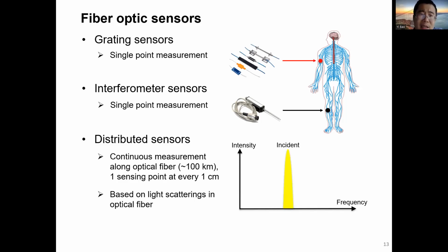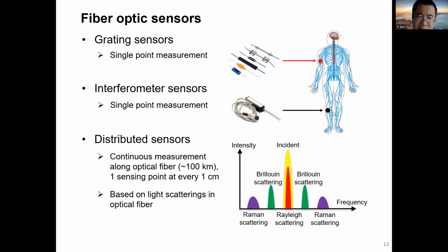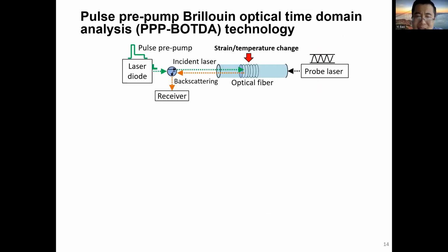So compared with the point sensors, people have developed distributed sensors, which can provide continuous measurements along the whole length of optical fiber, and the measurement length could be longer than 100 kilometers. This distributed sensing technology is based on light scatterings in optical fiber, including Rayleigh scattering, Brillouin scattering, and Raman scattering. In my group, we have used the Rayleigh scattering and Brillouin scattering based technologies because they usually have higher sensitivity, higher accuracy, and higher signal to noise ratio, because those scattering signals have a relatively higher intensity.